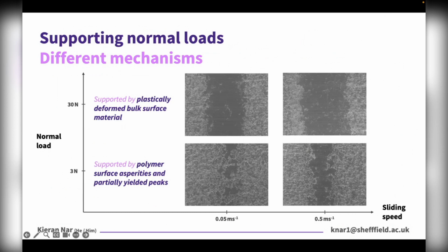Focusing back on the contrasting variations in sliding, we're able to attribute this to the mechanisms by which each normal load was supported during testing. The 30 Newton applied normal loads, which is our high load test condition, we found were supported by plastically deformed bulk surface material, whereas our low loads, so 3 Newtons in this case, were supported by polymer surface asperities and partially yielded peaks.